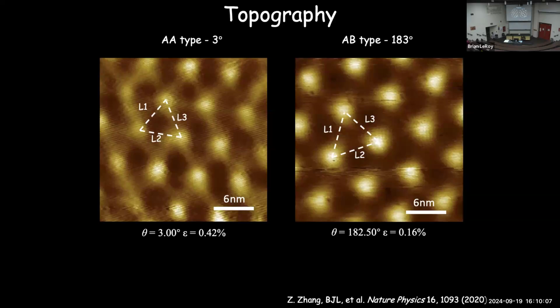And then we wanted to probe them, first from a topographic point of view. If you look at the topography here, the color scale is the height of the sample. White is high, dark is low. You'll see these look fairly similar. There's a series of white spots in both cases. Orientation may be slightly different from each other, but they have an identical periodicity. This 6 nanometer scale bar is about the periodicity here and here as well. So it doesn't matter what twist angle you have, you get the same periodicity between them.